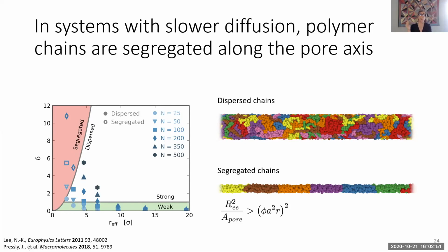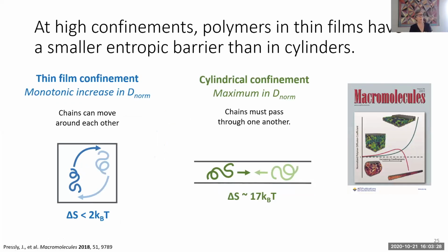And so now we can understand why there's a turnover in the diffusion coefficient, because as long as the system is dispersed and you confine it more, you reduce the number of entanglements, and that should allow things to move faster until you get to a point where you've segregated the chains. And now there's a huge entropic penalty for, let's say, the orange chain to move past the purple chain. They have to become very elongated to get past one another in this small diameter cylindrical pore. And that's what I've tried to represent here.